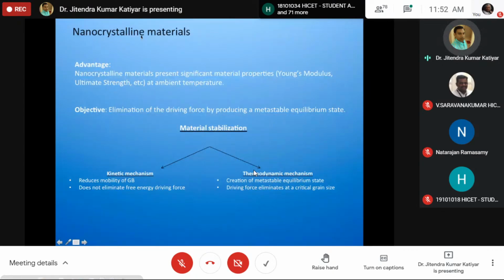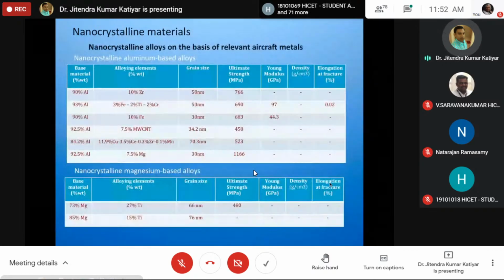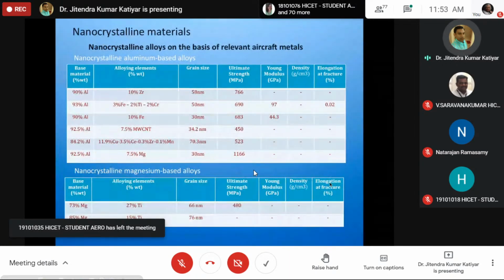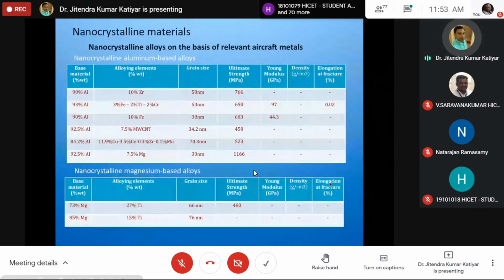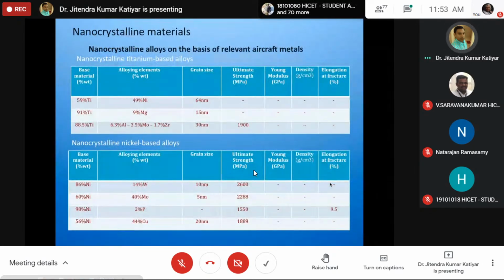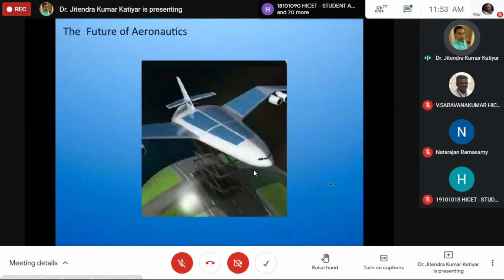By adding this nanocrystalline material, it can improve significant material properties at ambient temperature, and the objective is to reduce the driving force by producing a metastable equilibrium state. The kinetic mechanism is reduced mobility, which does not eliminate the free energy driving force. The thermodynamic mechanism is creating a metastable equilibrium state, where the driving force is eliminated at the critical grain size. So that is a very stabilized material, nanocrystalline material, which is also a future material for aerospace applications. These are a few mechanical properties of nanocrystalline material added in different base alloys: aluminum, magnesium, titanium, and nickel. We can check the particular mechanical properties according to our aircraft metal. So these are the future of aeronautics.